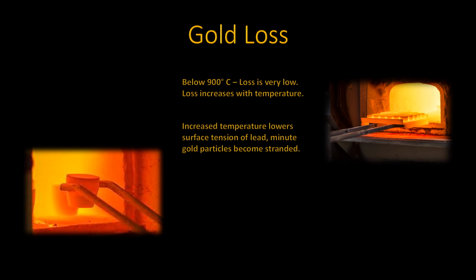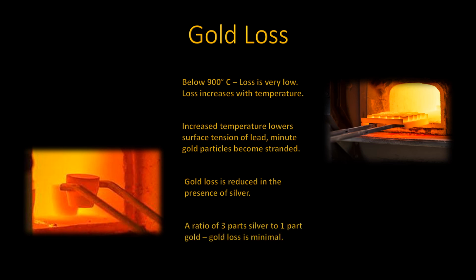A temperature increase will lower the surface tension of the lead, and minute particles of the lead will become stranded, oxidized, and then absorbed. As the surface tension lowers, the lead does lose the ability to hold and trap the gold as intended. However, gold loss due to absorption is reduced in the presence of silver. It has been found that with a ratio of 3 parts silver to 1 part gold, the loss of gold is negligible. More on this subject in an upcoming presentation on parting and inquartation.